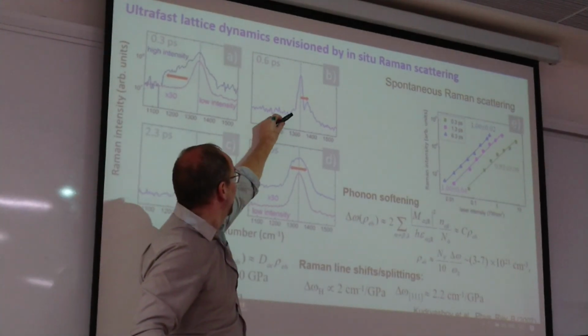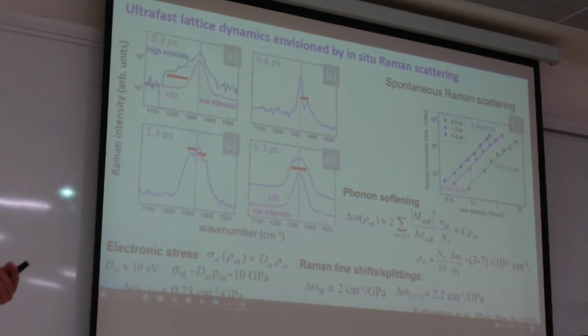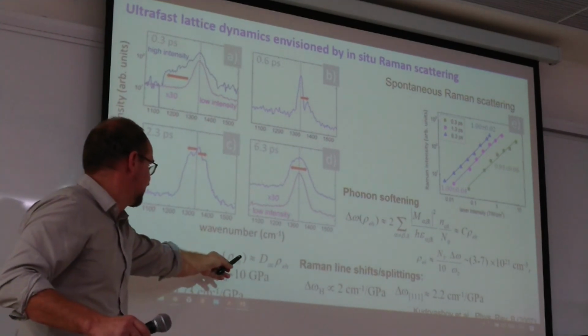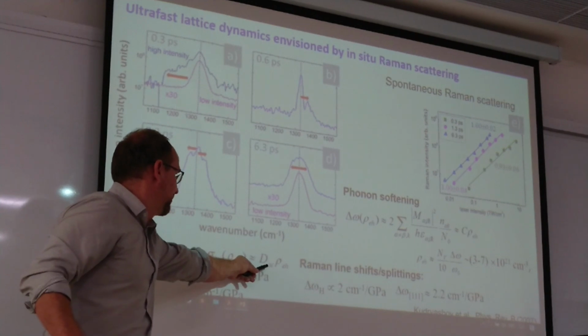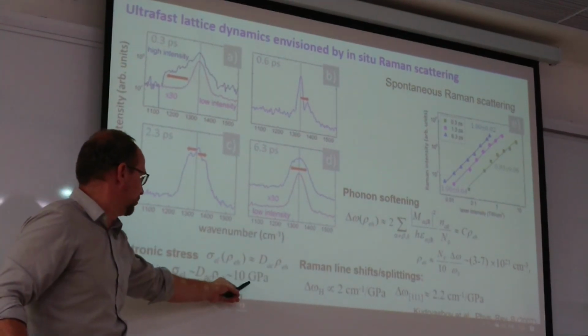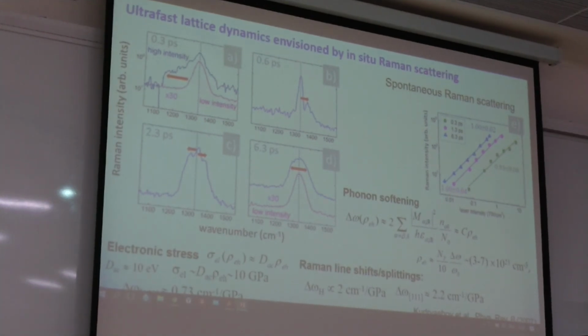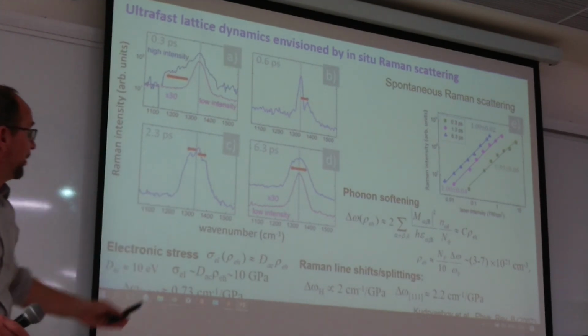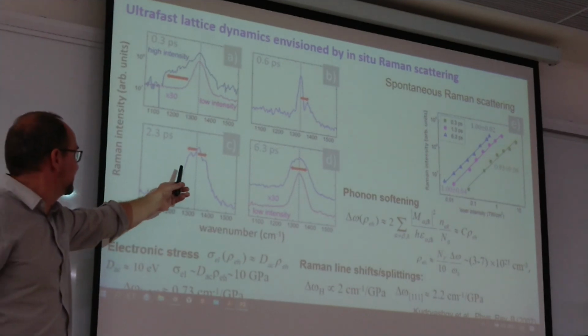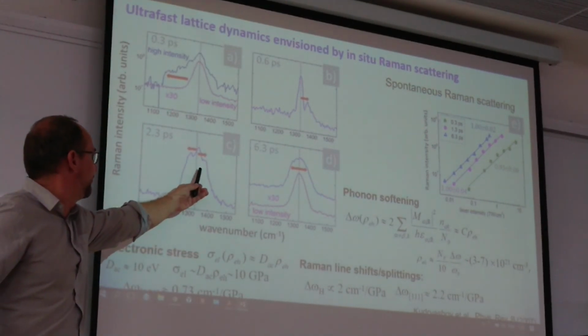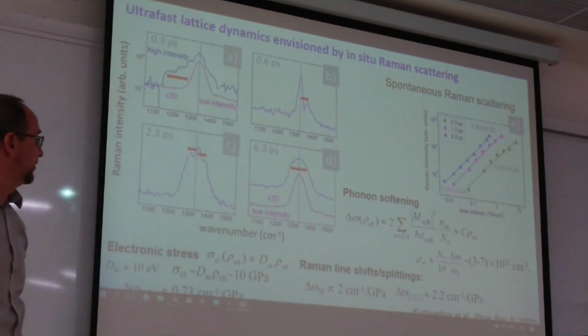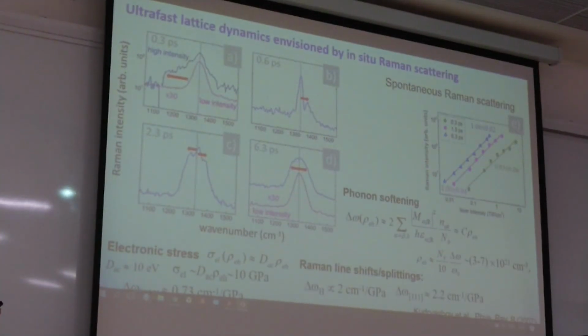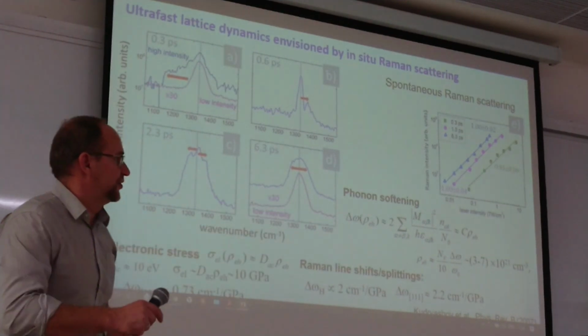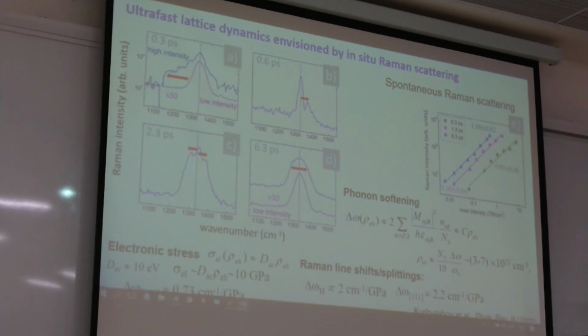At later times, we can see the line splits into two components, and this shows the local anisotropic pressure in the focal region. And we can evaluate this electronic stress considering the acoustic deformation potential and plasma density, and it goes to tens of gigapascals. Huge pressure, but very local, only in the focal point, which has micron dimensions. At later times, we have phonons generated in the focal volume and anisotropic stresses and splitting of the Raman line into three components. And at later times, we can see homogeneous broadening. Homogeneous broadening shows the stress is homogeneous, so there is just thermal stress around, and that's it.